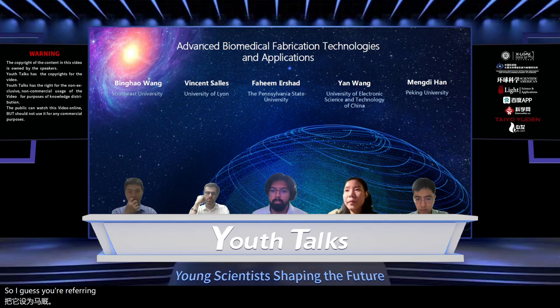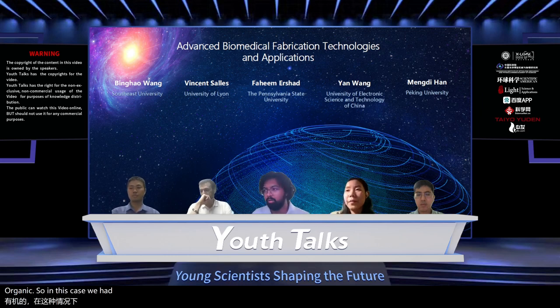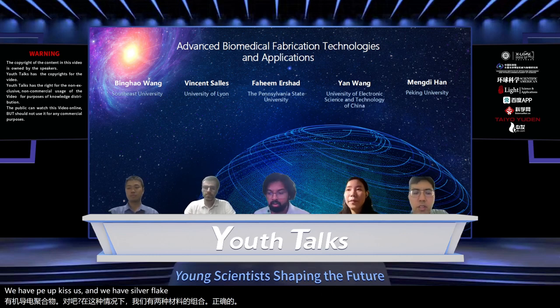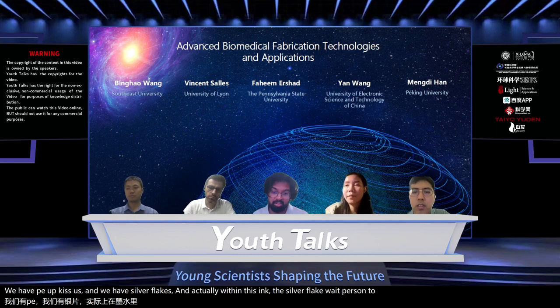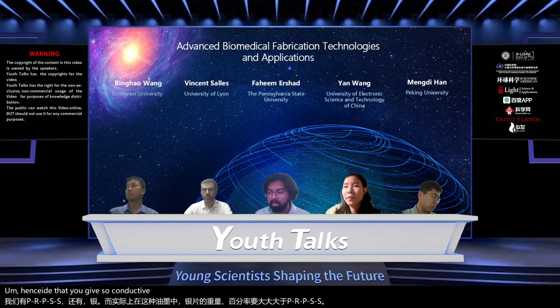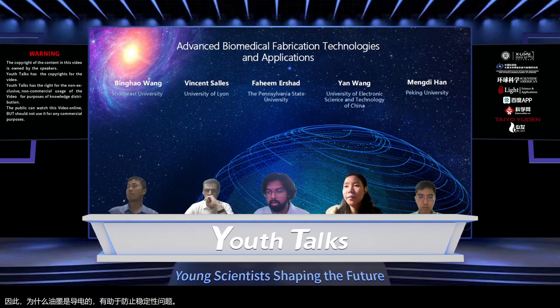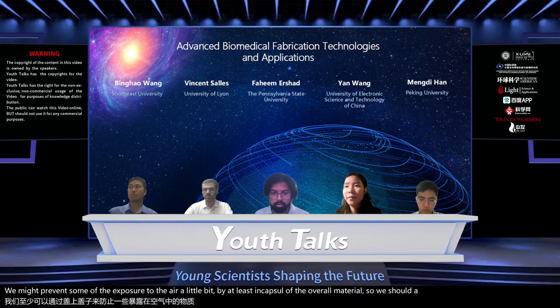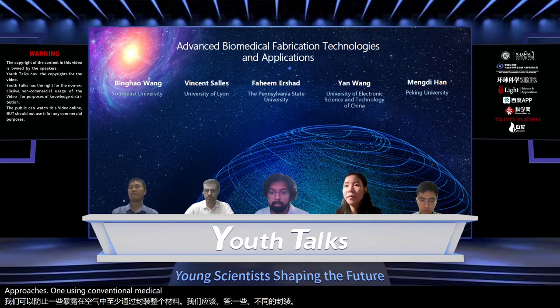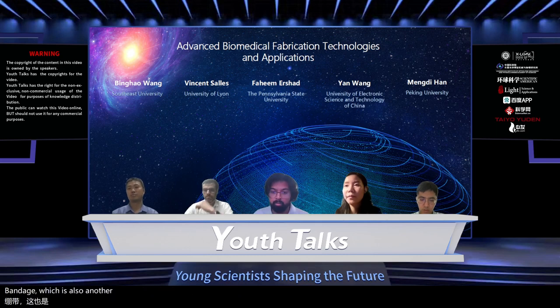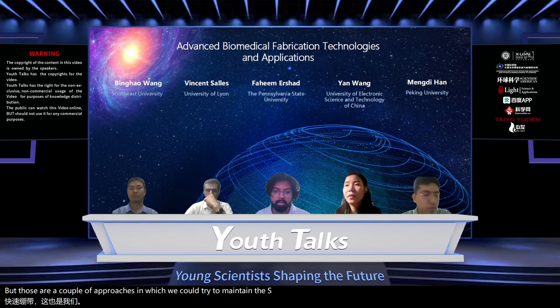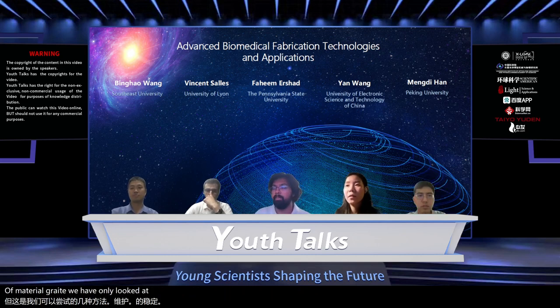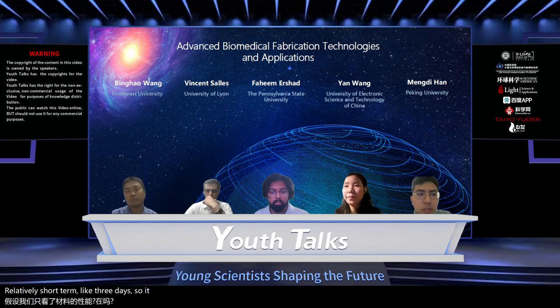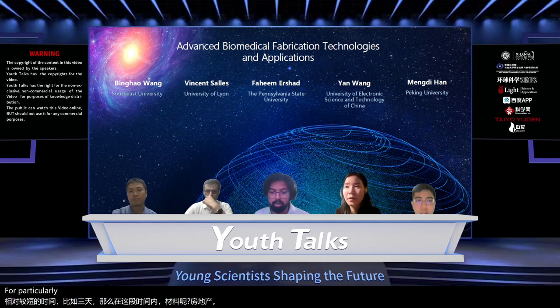So I guess you're referring to the PEDOT:PSS within the conductive ink, the organic conducting polymer, right? In this case, we had a combination of two materials: PEDOT:PSS and silver flakes. Within this ink, the silver flake weight percentage is substantially larger than that of the PEDOT:PSS, hence why the ink is so conductive. To help prevent issues with stability, especially with the organic conducting polymer, we might prevent some of the exposure to the air by encapsulating the overall material. We showed a few different encapsulation approaches, conventional medical tape, or for example a wound bandage, which is another one. Those are a couple of approaches we could try. Granted, we have only looked at the ink performance in the relatively short term, like 3 days. Within that time period, the material is stable for particularly electrophysiological applications.